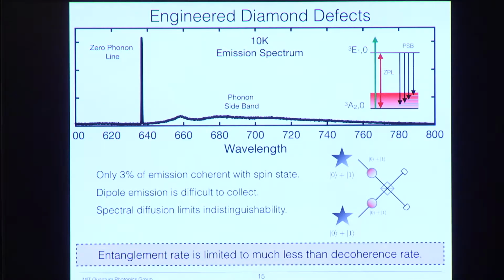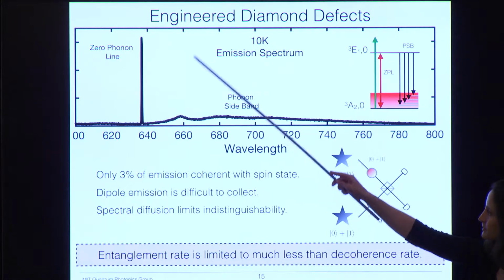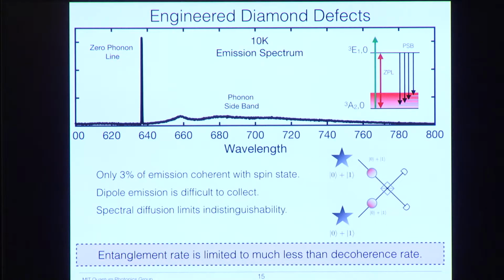And that's because although the system is nice, it's still trapped in a lattice. So we can still couple the spin to the lattice, and you get these phonon transitions. So any photon that comes out in this phonon sideband comes from a decay event plus a phonon decay. And when that phonon decays, it loses all its information to the lattice, and so that photon cannot be used for quantum information processing. So we can only use these photons, and that's unfortunately only 3% of the emission of an NV center in bulk.